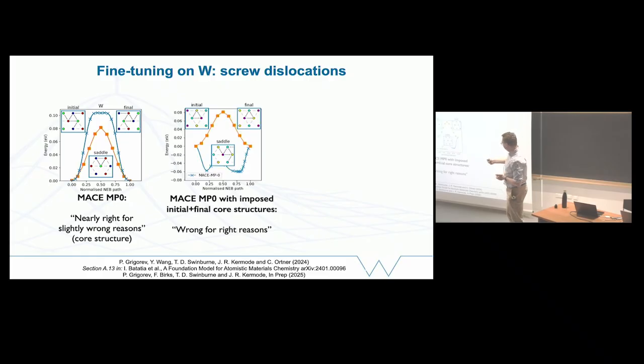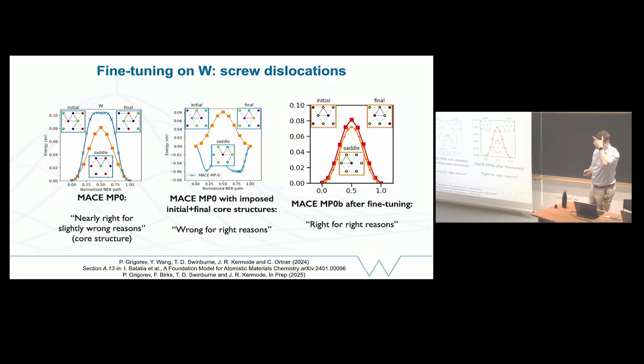If you do relax the cores, or you impose the correct core structure, then actually it's not stable. So we did manage to break the foundation model for the transition state here. But if you fine-tune it, you get the right answer for the right reasons. So you get the right core structure, the right saddle point, and a pretty good barrier quite cheaply. So I think in future I will make more use of these foundation models in my research group. We'll use them as a starting point. We'll add a little bit of our own data rather than building exhaustive data sets.